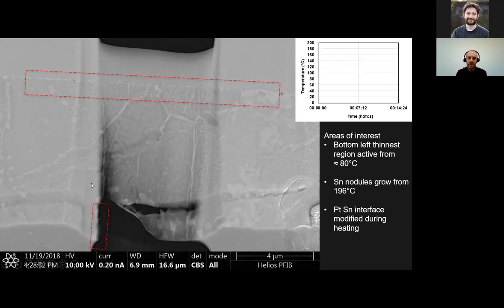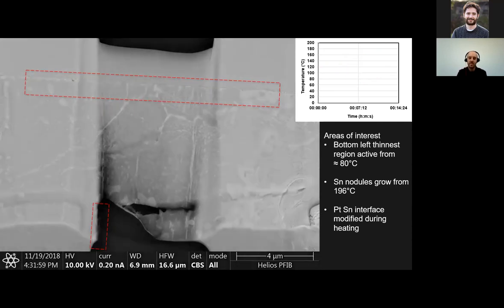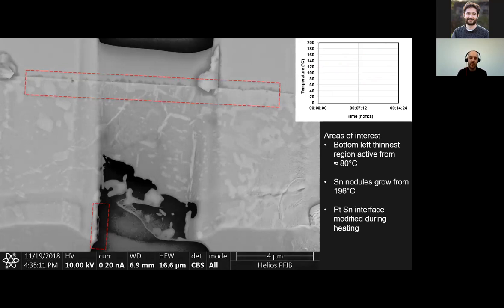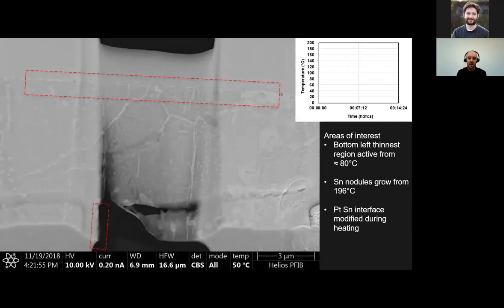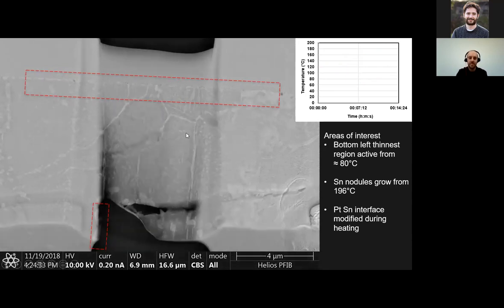There are a few things we initially learned from this. One, it's very difficult to decide when your sample, in this case a tin sample, is molten or whether you're just seeing surface diffusion going on. The other thing was your surface coatings matter a lot. This platinum layer was clearly reacting with the tin.